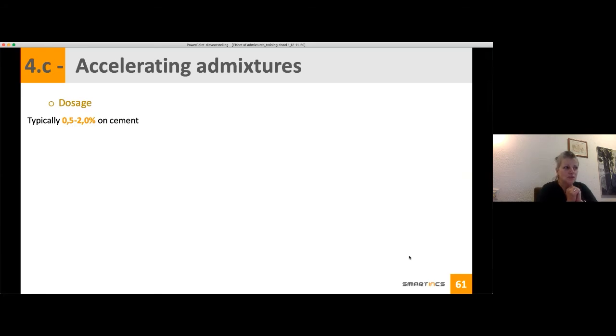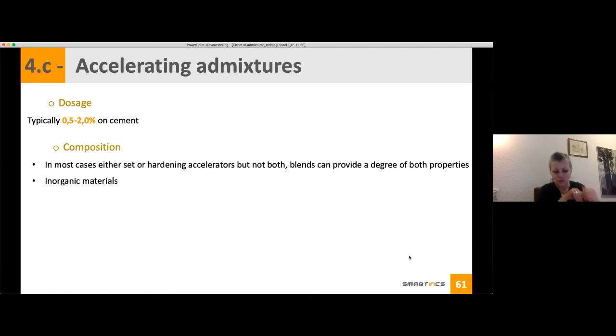If we look at the dosage for the accelerating admixture, it is typically 0.5 to 2% on the cement weight. In the composition, usually you have one of the two effects. So it's either set accelerating or hardening accelerating, but rarely both of them. And they are largely based on inorganic material.